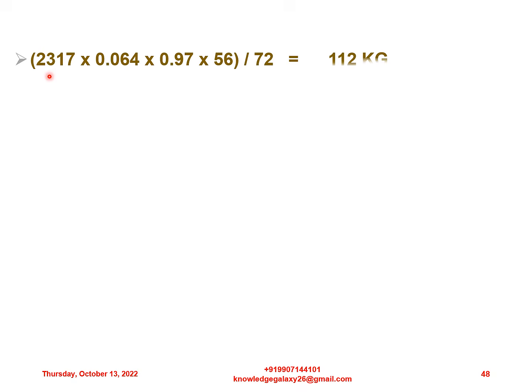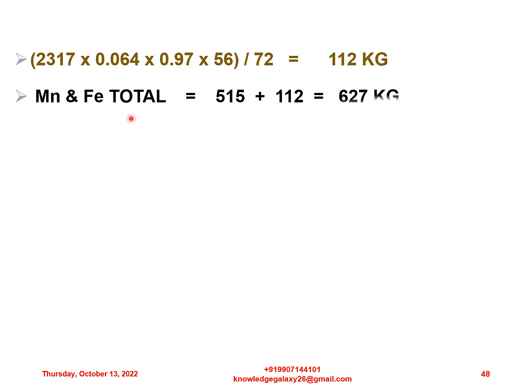It comes to 2317 into 0.064 into 0.97 into 56 whole divided by 72. Here 0.064 is the 6.4% content of iron in ore, 0.97 is the 97% recovery of iron, 56 is the atomic weight of iron, and 72 is the molecular weight of FeO. It comes to 112 kg. Mn and Fe total comes to 515 plus 112 equal to 627 kg.